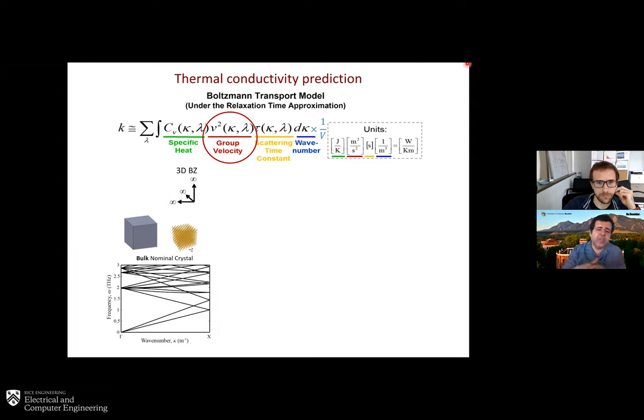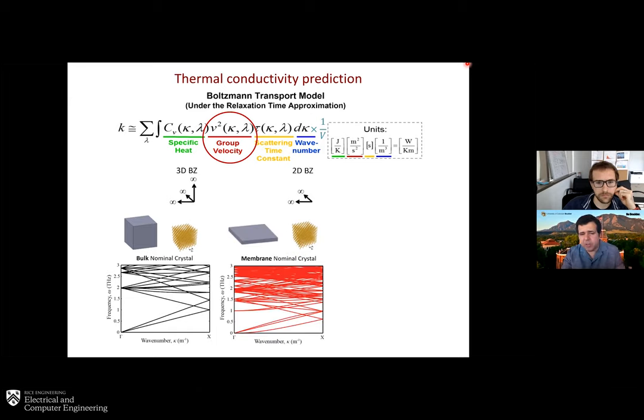So naturally, you'd think, okay, what if we turn this bulk material into a membrane? If we turn it into a membrane, then because of phonon confinement effects, we're essentially flattening the modes. This is well known even at the continuum level when we look at plates, for example. You get a flexural mode and shear modes and so on. So these are non-bulk type modes, and they tend to have lower slopes, so they have lower group velocity. With that approach by itself, by just reducing the dimension, you can reduce the thermal conductivity. However, it's not enough if you're pursuing high thermoelectric performance.